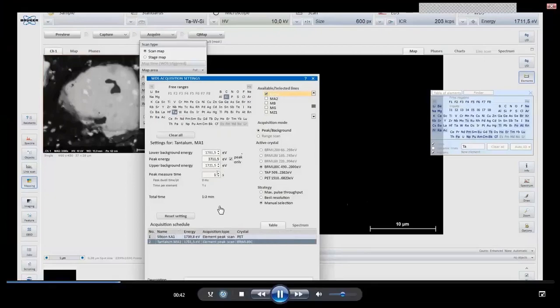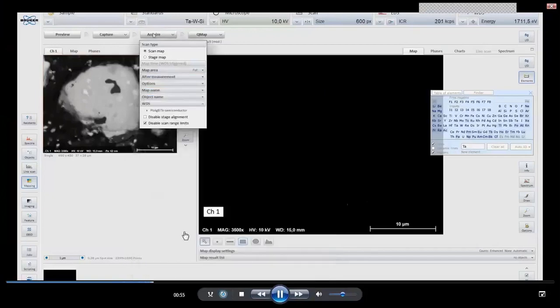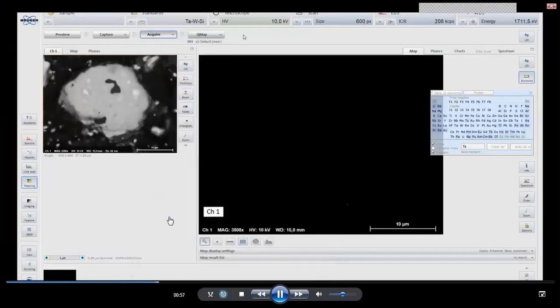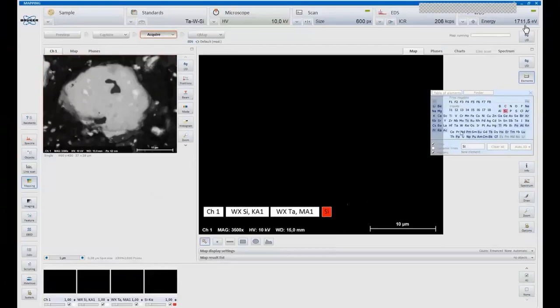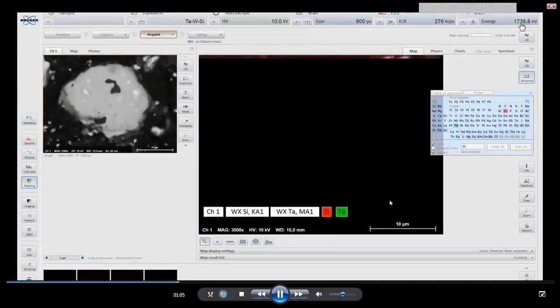We set a second element. After silicon, we now set tantalum as the second element. So 2 different energies will be mapped, and we start the acquisition here. On the upper right, you can see the WDS configurator, and you can see the energy that is currently scanned here.